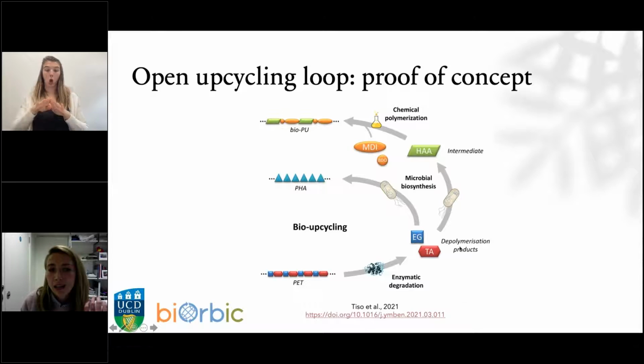So what happens there? As I explained, you have PET as a starting material, you enzymatically degrade it and get ethylene glycol and terephthalic acid, and you've seen that we can produce PHA. But what we also were able to do is incorporate a synthetic pathway in this bug. And now Pseudomonas umsongensis not only can produce PHA, but it can produce hydroxyalkanoic acids that we then use in chemical polymerization, and we have made a novel biopolyurethane, another type of plastic. So we have made a novel type of bio-based plastic.